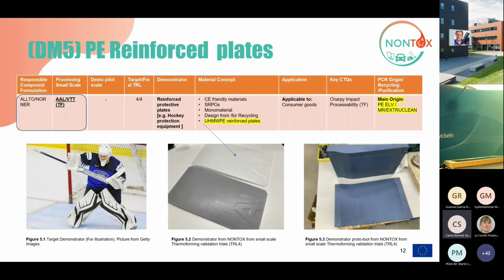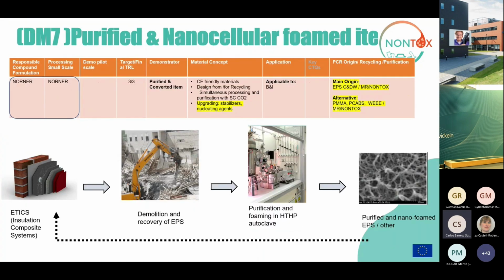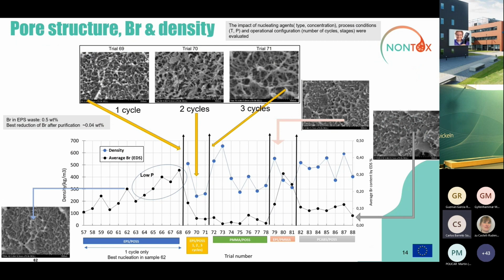This other demonstrator was on the use of laminates of polyethylene from recycled ELVs devolatilized by Extruclean that were reinforced by ultra-high molecular weight PE mats. This other, it was the purified nanocellular foam that was quite successful, taking EPS from construction and demolition waste. The material was upgraded with stabilizers, nucleating agents, and by a multi-cycle process in batch autoclave,